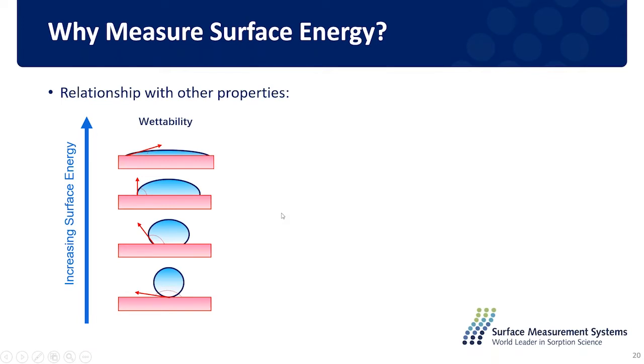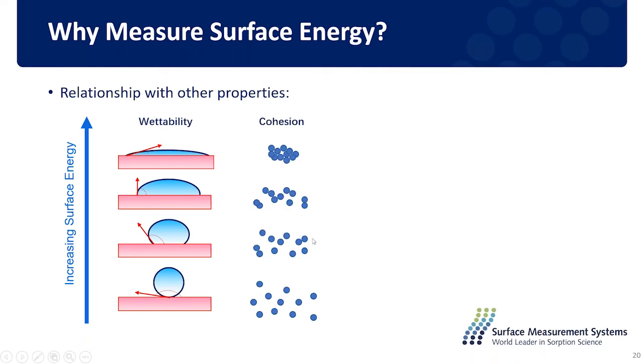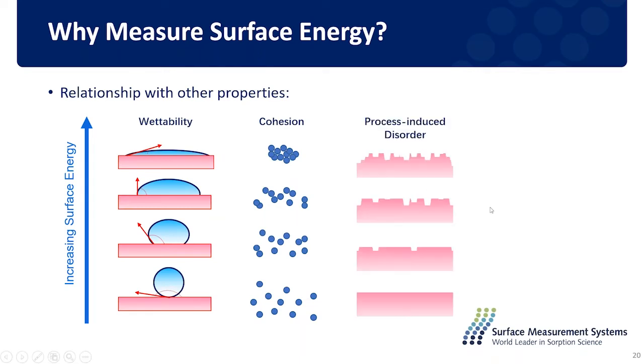And we need to measure the surface energy of different kinds of material because surface energy is related to quite a lot of thermodynamic properties. So for example, if a sample has higher surface energy, the surface of that material has a better affinity with water, so it will have better wettability. And also, if a particle has a higher surface energy, the particle-particle interaction will be higher. That will result in aggregation of the particles themselves.